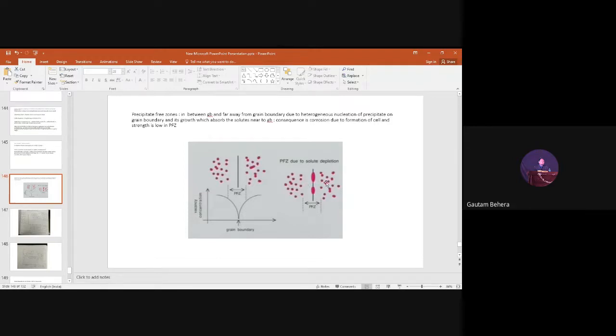So basically this happens due to heterogeneous nucleation conditions. If particles are not forming everywhere in the material and there is heterogeneous nucleation, with some preferential sites to form precipitates, this kind of situation may happen. Formation of a galvanic cell may happen and corrosion may take place, right? Two things are happening. One is a decrease in the strength in the precipitate free zone, and the other is that a galvanic cell may form over there, right? Okay, so this topic is ended.